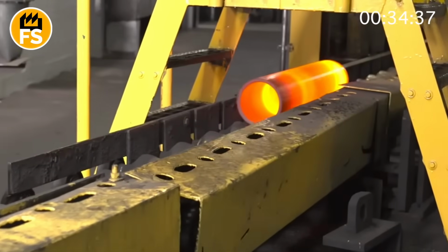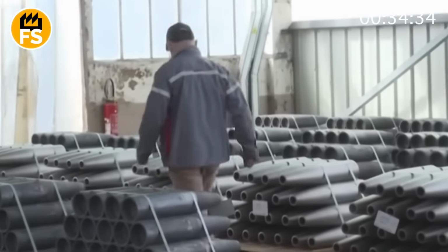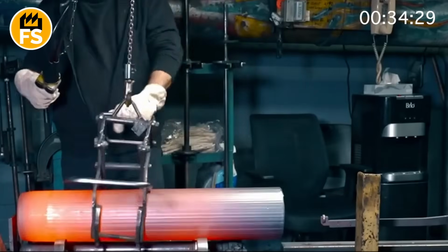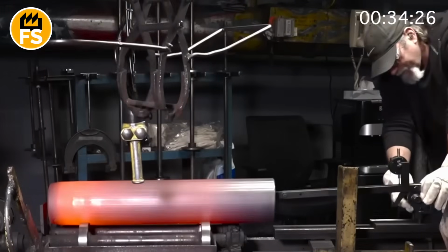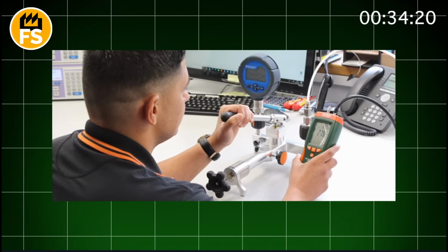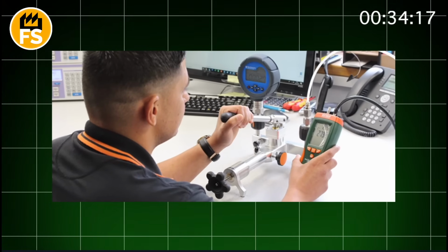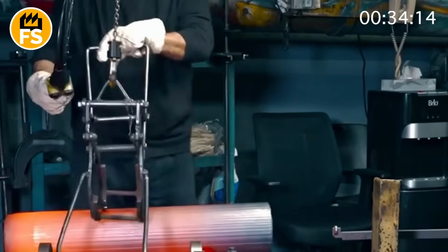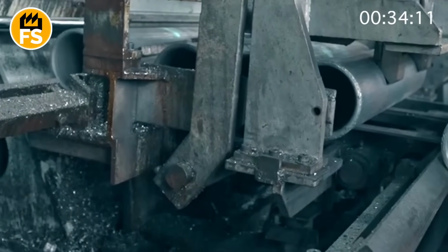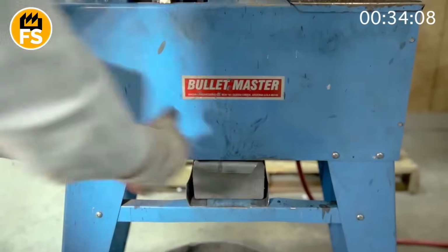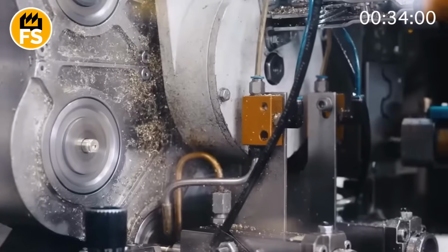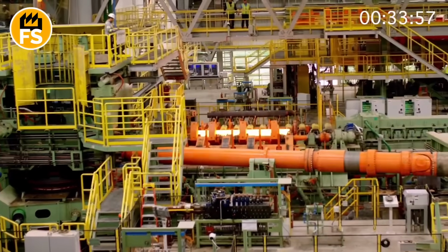Rotating blades or milling cutters cut off the excess length. For example, for a large artillery shell, the typical casing length is 15.6 inches. This is accuracy not by eye, but to the thousandth of an inch. After this, the part passes through a calibrating unit. This is either crimping rolls or boring systems with precision micrometers. The casing diameter must match the standard plus or minus 0.001 inch. Otherwise, the shell will either not enter the gun's chamber or will get stuck. At the output, we have a part ready for further processing, with clear geometry and parameters.